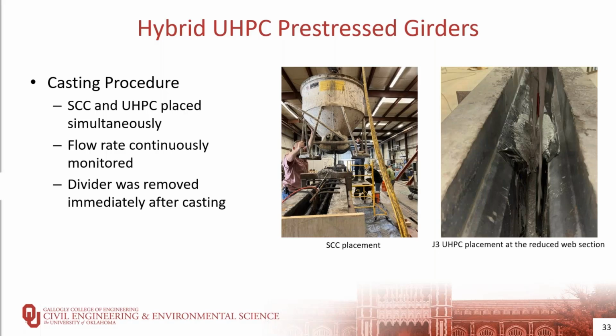And to make this casting process a little bit easier and to get a better interface between the two concretes, a couple of people were actually casting the SCC while some other people were at the UHPC end waiting to see the SCC starting to flow close to the interface. And then when that happened, we started pouring UHPC using 5-gallon buckets filled with UHPC. Then visual observations throughout the cast were made to control the flow of each mix and to maintain equal heights of both materials while casting. The divider at the interface helped to control the flow rate of both mixes.